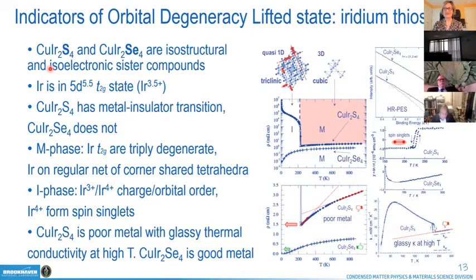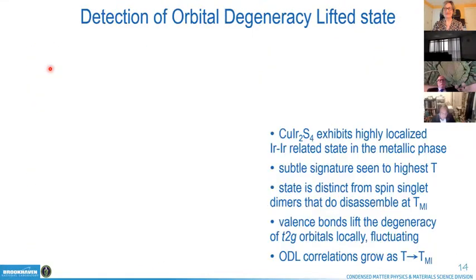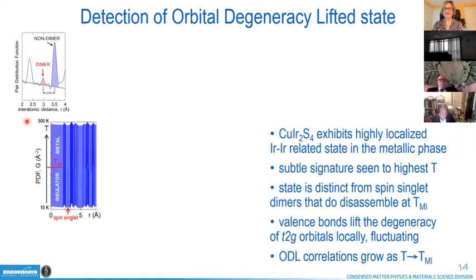And one natural thing that you can inherit from manganite logic is that maybe, just maybe, those dimers survive in the high temperature phase. That has been implicated theoretically. And so the signature of dimers in structure is that it has this short metallic bond. So this is the iridium-iridium bond that is non-dimerized, and then a fraction of iridium dimerizes at low temperature, and it creates this small peak. Well, then it should be relatively simple in PDF to explore if the dimers survive in the high temperature phase by simply plotting the waterfall plot of all the data spanning a broad temperature regime from low temperature to high temperature. And as you can see here, this little peak, which is a dimer peak, clearly disappears in the metallic regime. So to our disappointment, the answer was that the dimers disappear even locally at high temperature.